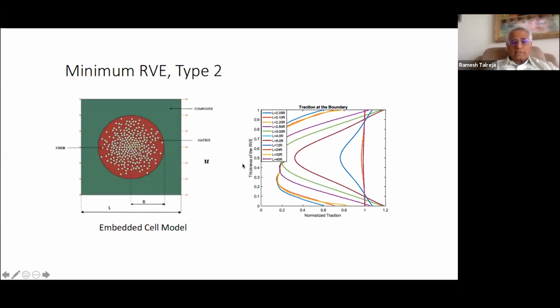The other type is where the final pattern is not rectangular. So what is done is to encircle it with a circle and then embed that. That is called a cell. Embed the cell in an outer region. Now, why? Because this is not totally suited for applying boundary conditions. So it's done commonly in the literature, not so commonly, but this idea is out there that you do an embedded cell. So the outer region is a homogenized composite. It has straight boundaries. It's, in this case, a square region. And then we use the Hill idea. The Hill idea is that if I apply to the boundary uniform displacement and I get uniform traction resulting from it, then I'm fine.